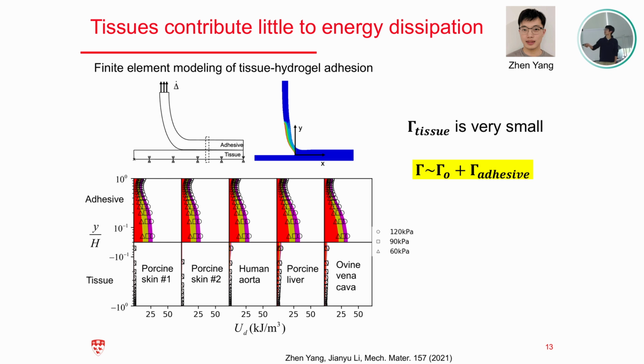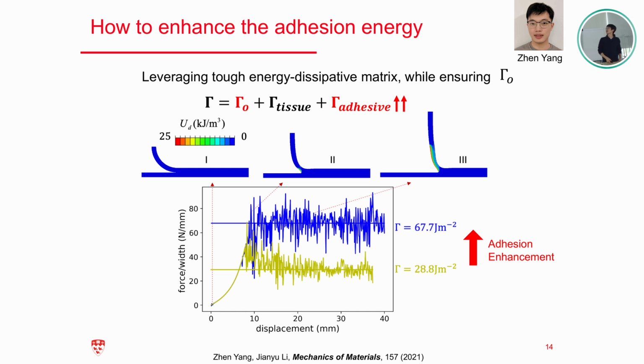So here is a summary of those results. We found that a significant amount of energy is only dissipated in the adhesive, and the tissue only does a little work. So what it indicates here is that the second contribution, the tissue substrate, is very small, right? And the last knob you can tune actually goes to the adhesive matrix. So the adhesive matrix is something we can rationally design.